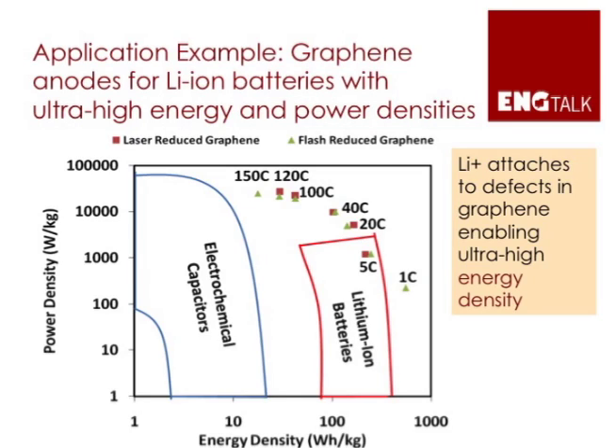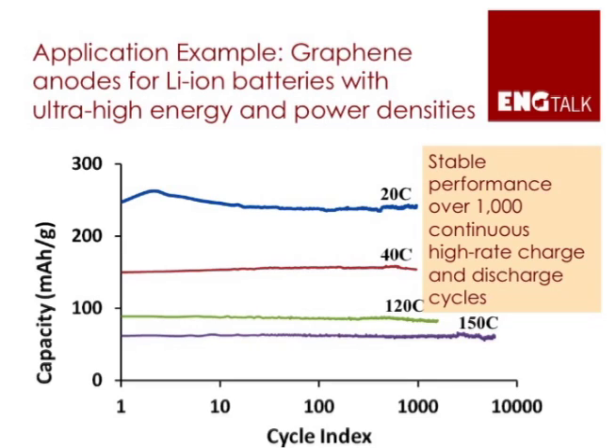On the next slide, I've shown a plot with power density on the y-axis and energy density on the x-axis, marking the regions for classical capacitors and batteries. Our system has significantly more energy density than an existing battery, but we also have higher power densities. If you want to charge your laptop in minutes rather than hours, you need power density — existing batteries take hours because lithium ions take a long time to diffuse into the structure. With our expanded open pore structure, the diffusion distances are much smaller, so we can pump lithium in and out at very high rates, achieving both very high power densities and very high energy densities.